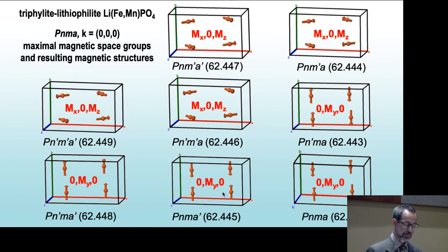Using the Bilbao crystallographic server, you can easily display the allowed possible magnetic structures where the propagation vector is 0, 0, 0, so the magnetic cell and the nuclear cell are the same size. And you can see the moment orientations for the 4 magnetic M2 sites and the allowed moment components. In this case, MX and MZ are allowed.